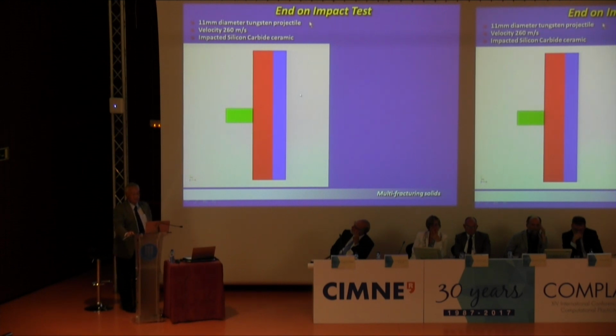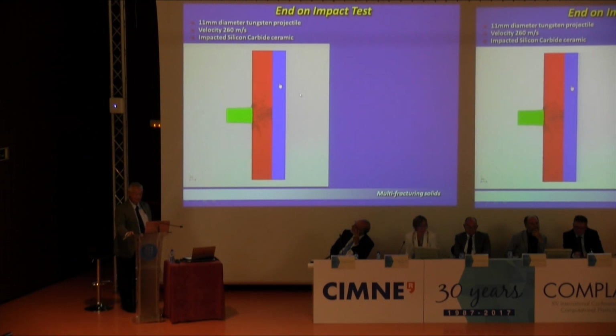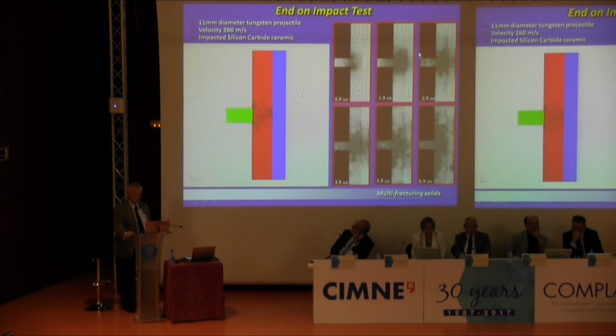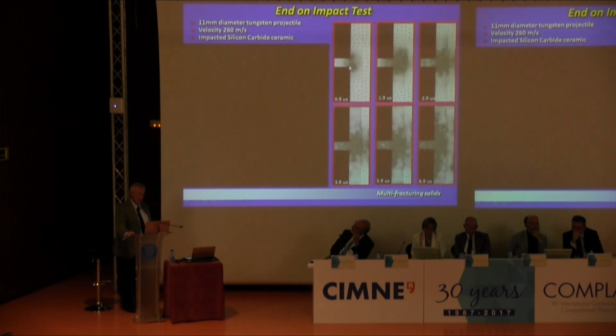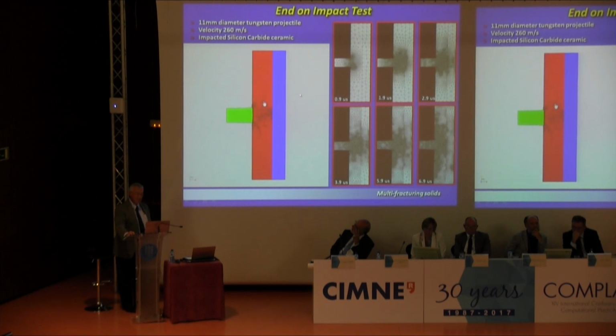Right, this is an end-on impact test, very quickly. It's a case of a tungsten projectile hitting a ceramic material, silicon carbide. This is a steel plate at the back. The reason I wanted to show this one is because it shows what you have to do: you can start off with a coarse mesh, and as the fractures develop, you have to remesh in order to capture the crack propagation between elements. So you start off with a coarse mesh, and you end up with a fine mesh here, which is a state which captures all of these fractures.